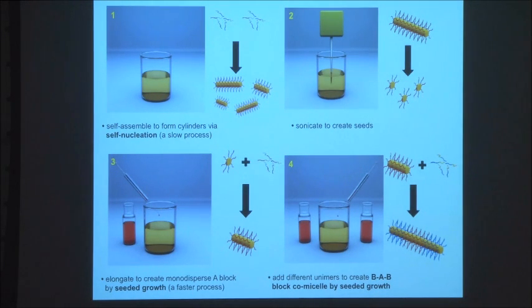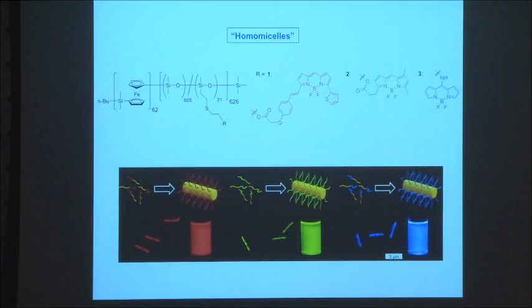And so to illustrate the flexibility of this, here's some recent work we've done using PFS polyferrocenylsilane block copolymers, where we've attached different color fluorescent dyes to the coronal block. So you can make this material with a red dye here, or a green dye here, or a blue dye. And if you take each of these materials individually and self-assemble them, the one with the red dye, of course, will give micelles that fluoresce red. The green will fluoresce green, and the blue will fluoresce blue.